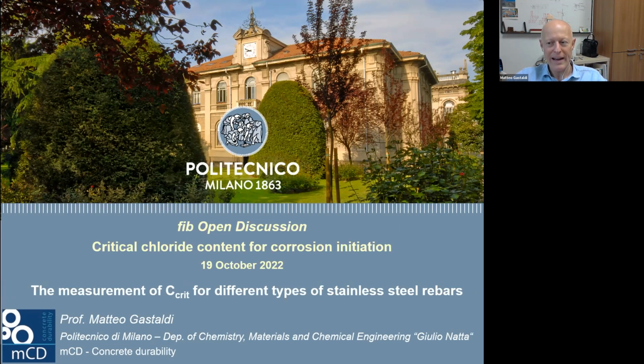The sodium chloride gives a chloride threshold that is higher than the chloride threshold that you can find with calcium chloride. That is a salt that gives a strong effect because the sodium chloride has sodium inside, and so this probably helps to reduce the problem related to initiation of corrosion. This is to answer this question.